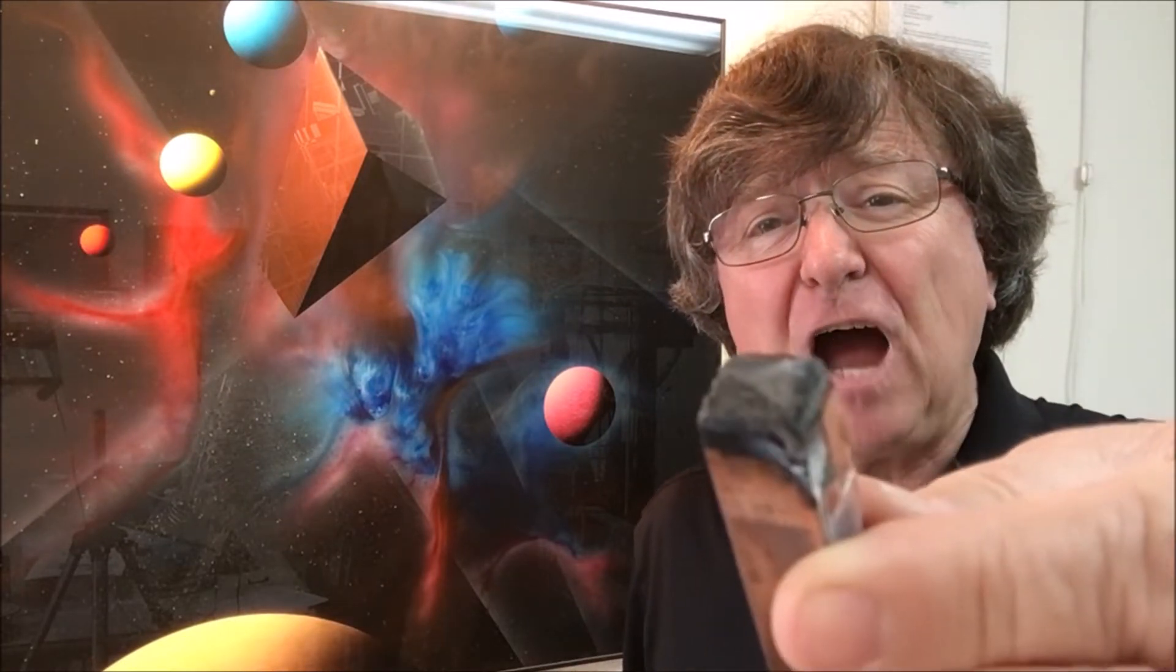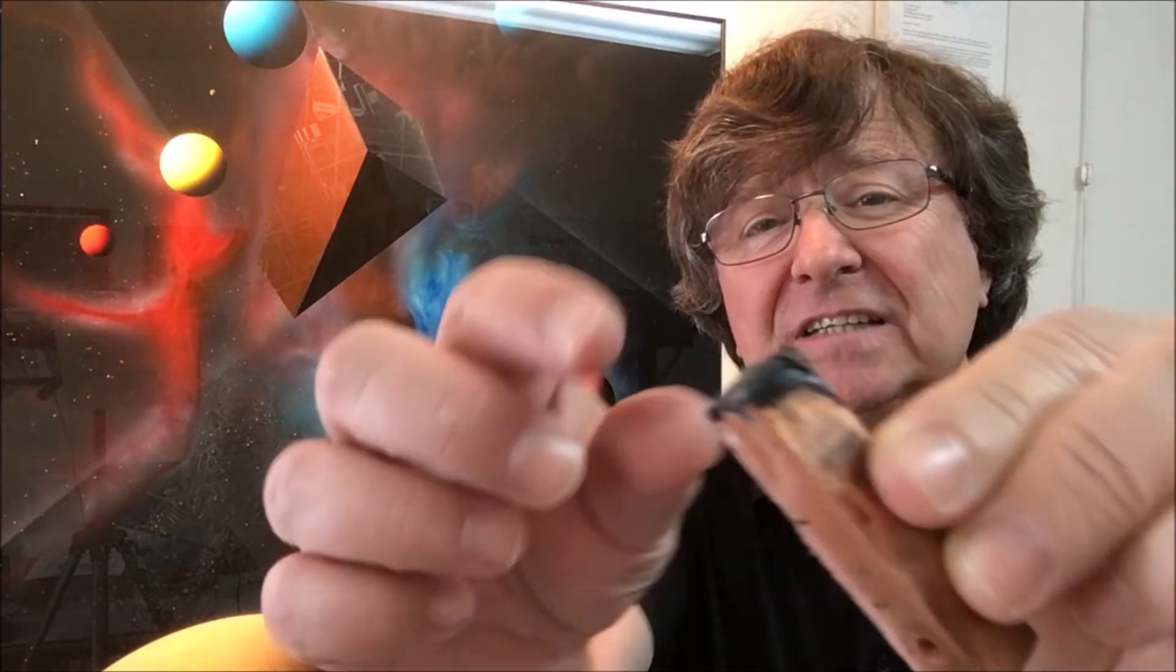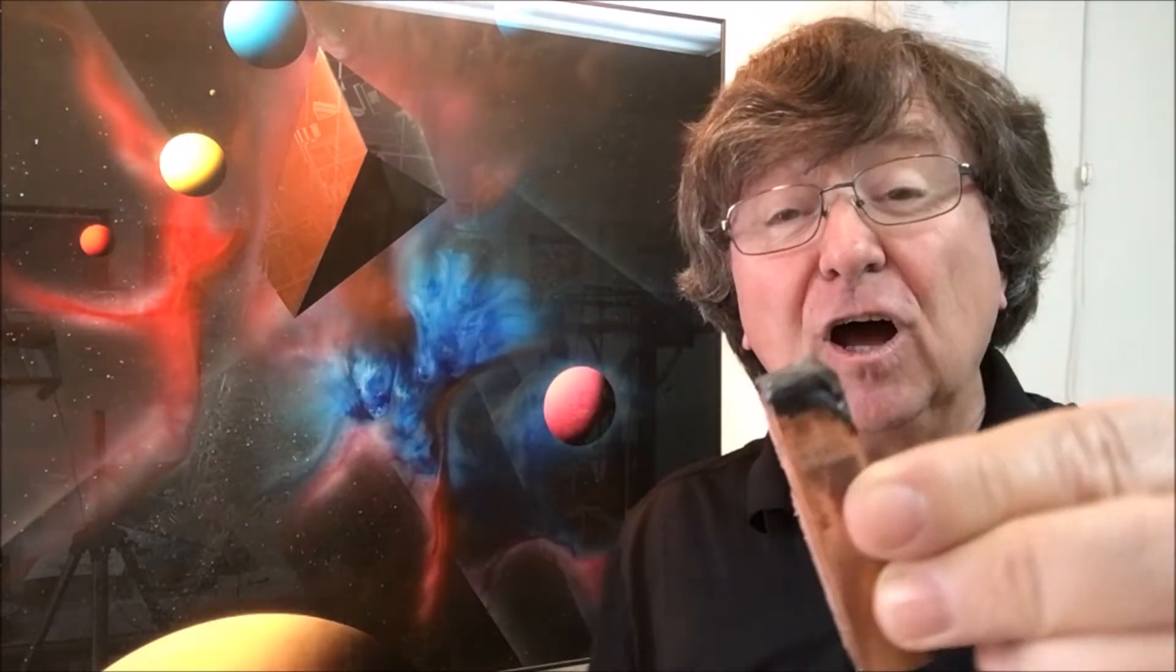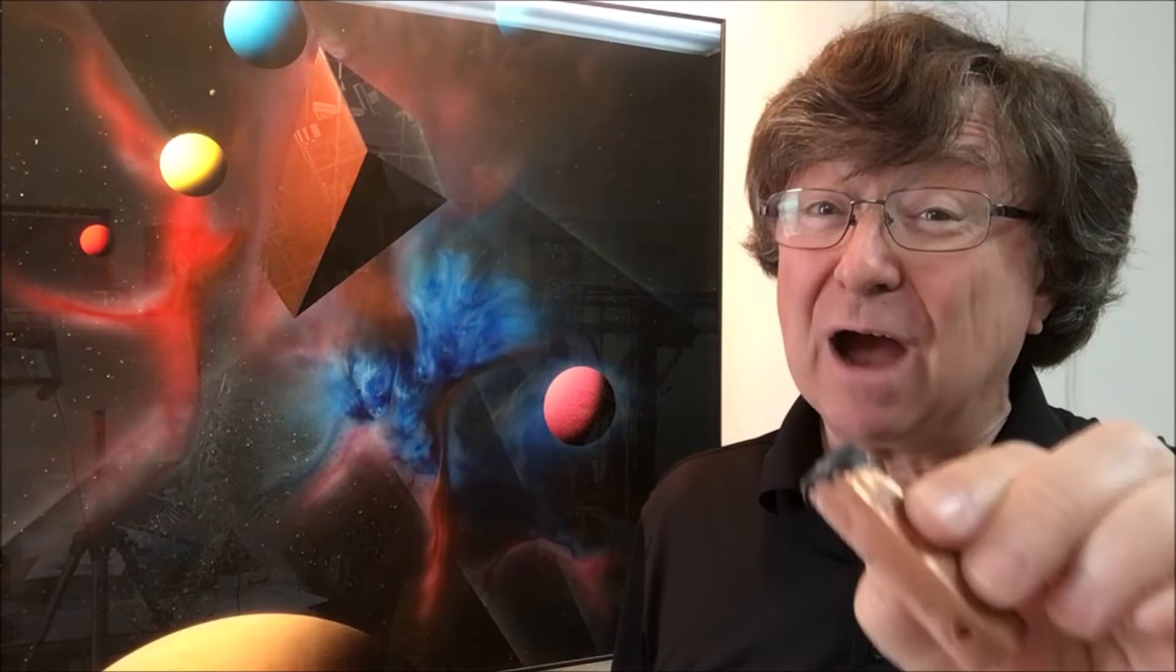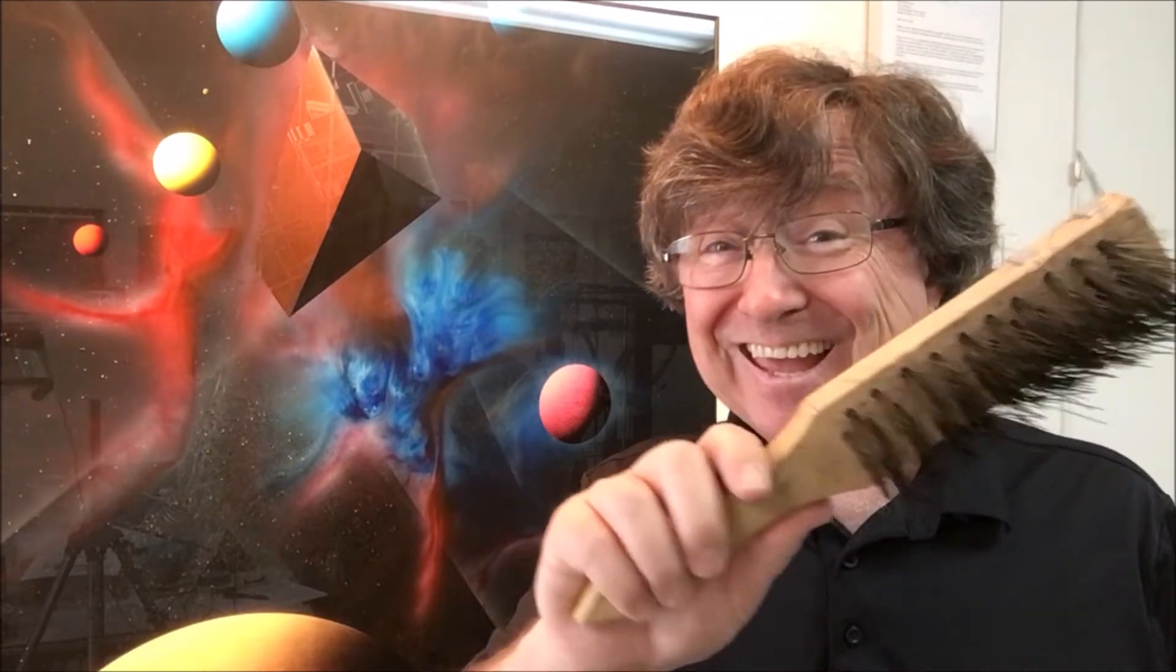This is a copper electrode after a firing. Some of it flakes off, but most of it has to be ground off. Here in this chart you can see the power drop off. It is caused directly by the fouling of the electrodes. The problem is you can't get in there with a wire brush and clean it while the motor's running.